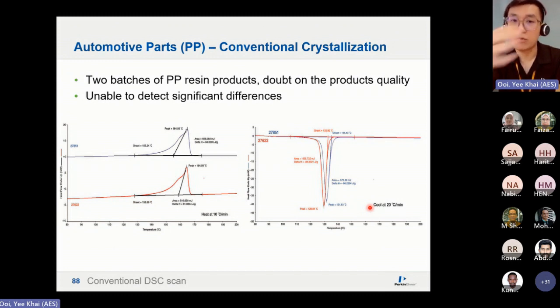So this is one example from Proton. Basically, they claim that they have two batches of raw materials, polymer. When they heat up, one is okay, one is not. When you heat up, this is the melting, this is the crystallization. Both results are comparable, or there is not much difference. They were unable to detect significant differences using the conventional heating or cooling rates, so 10 degrees C, 20 degrees C.